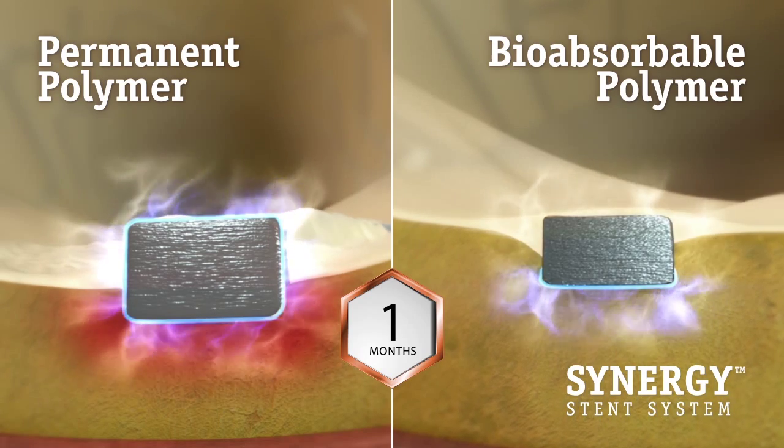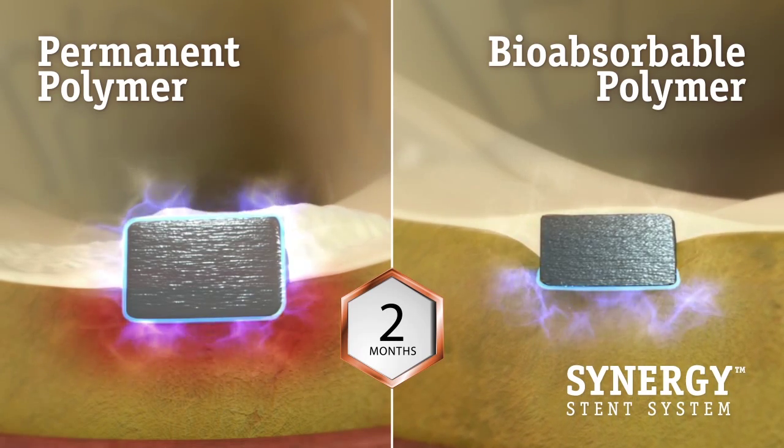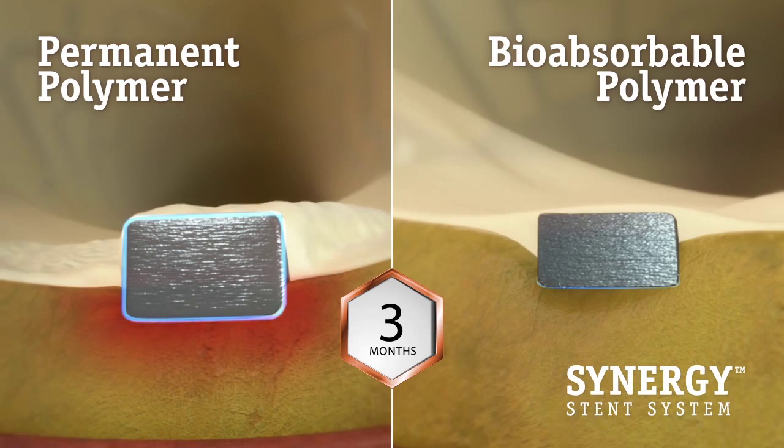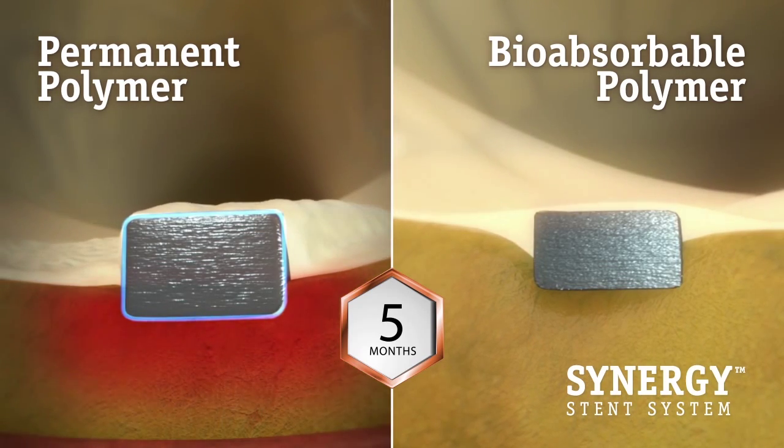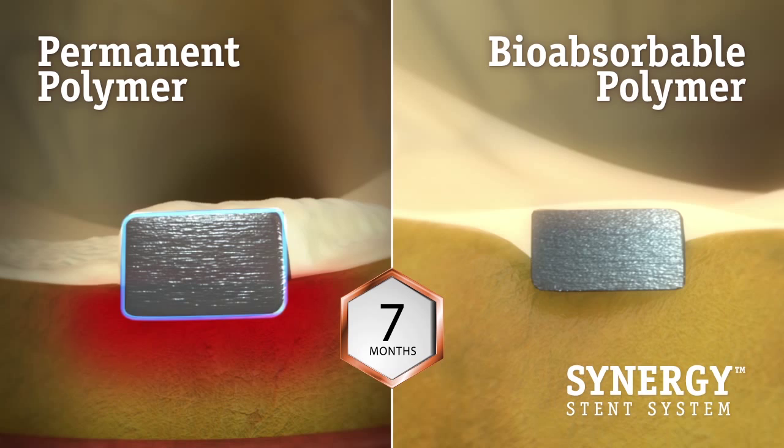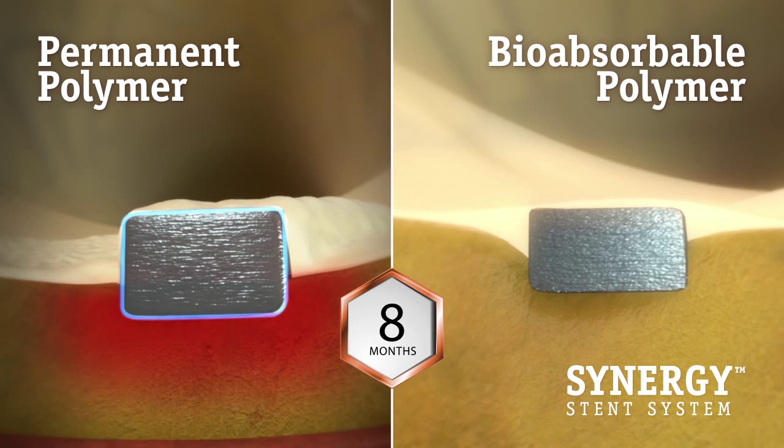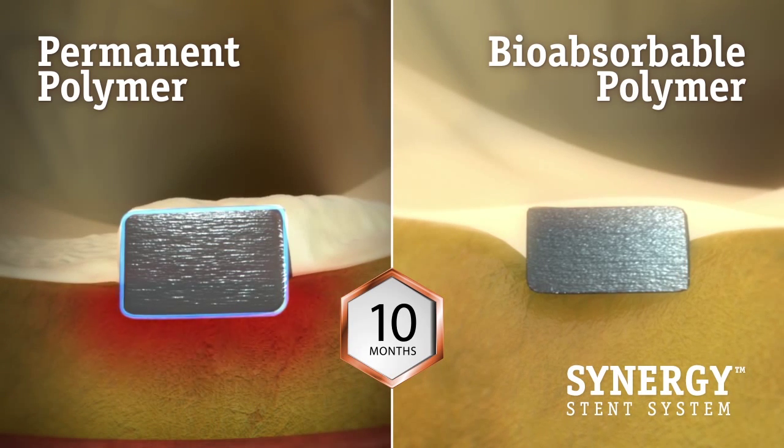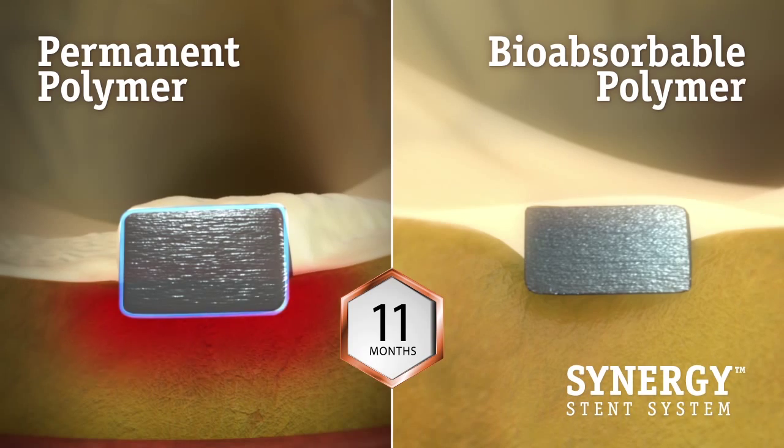With the Synergy stent, shortly after the drug is released at 3 months, the polymer is fully absorbed, allowing the vessel to heal and providing patients with freedom from long-term polymer exposure, eliminating a source of persistent inflammation and potentially reducing the risk of late stent thrombosis.